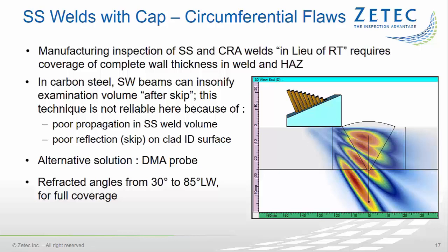In carbon steel welds, shear wave beams are used to insonify the examination volume after skip. For CRA welds, this technique is not reliable because of the poor reflection on the clad ID surface, and also because of the poor propagation in the austenitic alloy weld volume. For homogeneous stainless steel welds, the shear wave beams can be used for base material examination only.